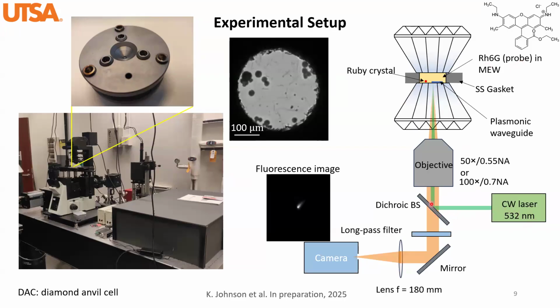We shine a 532 nanometer laser and focus the objective on the plasmonic waveguide, and it will excite surface plasmons. As the surface plasmon propagates, it interacts with the dye molecules and causes fluorescence of the dye, even if the dye is away from the laser excitation. We collect the fluorescence of the dye molecules, filtering with a dichroic beam splitter and a long pass filter, and then collect the fluorescence image. This is an actual image of a nanowire when we shine at one end of the wire. You see that the surface plasmon propagates along the nanowire.